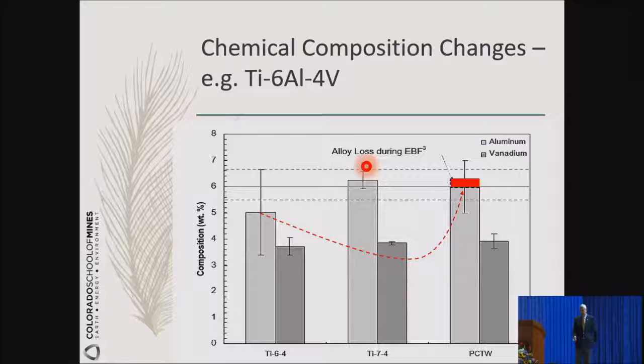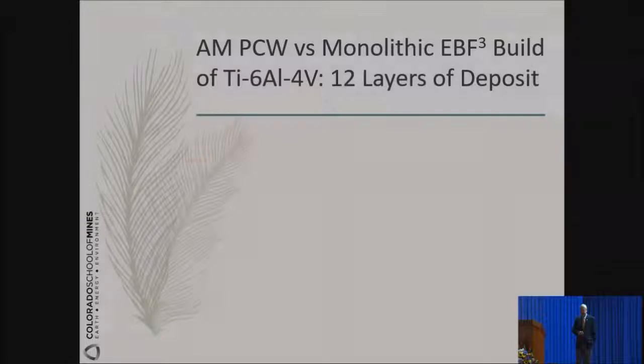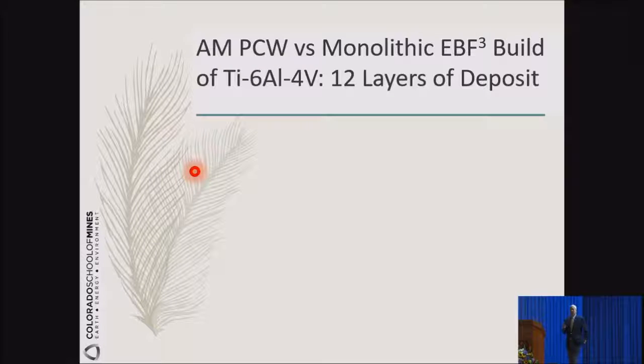So what we have done was to use a powder core wire. You put your correction of the chemical composition into this powder core. And then with that, you see here, your alloy composition falls back to the original 6% of the Ti-6-4. So it is possible to do that. And so here I will compare for you 2 different processes. One using what we call the monolithic Ti-6-4. The other one is the powder core Ti-6-4, so that you see the differences between them.